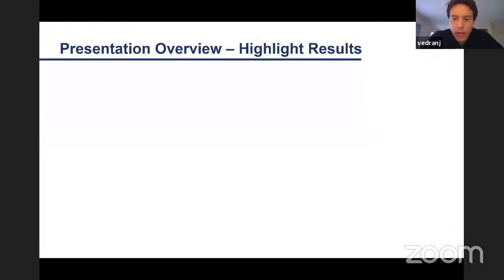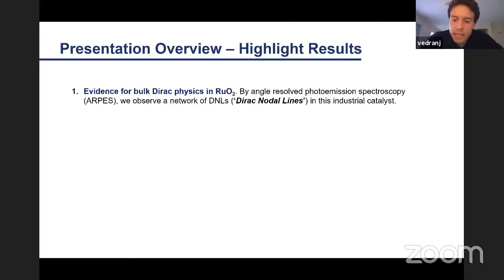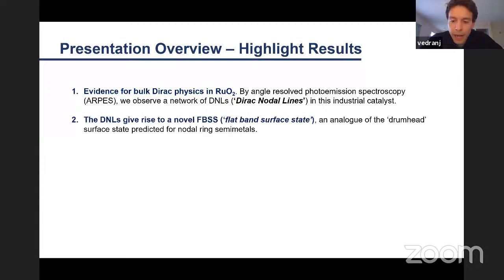Before I get into an outline, let me start by highlighting some of our key findings from these studies. These results were some of the first reports of bulk Dirac physics in a functional oxide, ruthenium dioxide, a material with really concrete applications. Using angle-resolved photoemission, we observed a network of Dirac nodal lines at the Fermi surface. The Dirac nodal lines give rise to what's called a flatband surface state at the Fermi level. It's an unobserved analog of the drumhead surface state predicted for nodal ring semimetals.